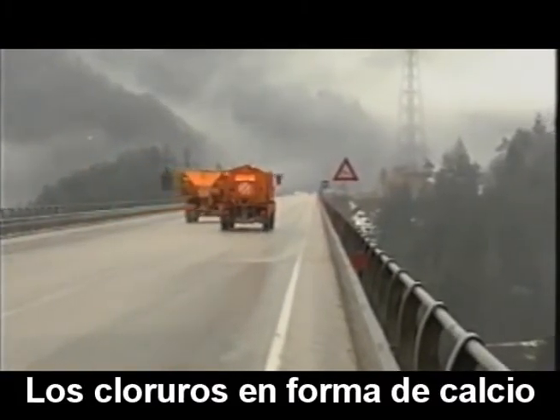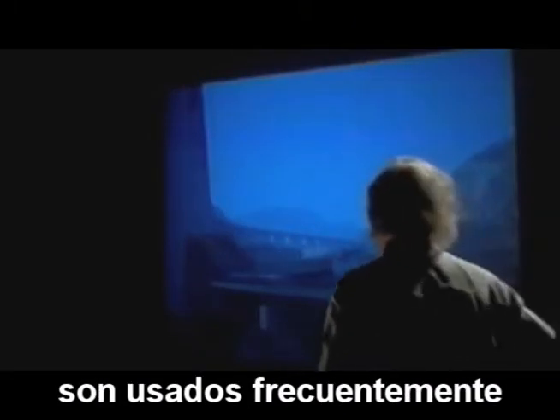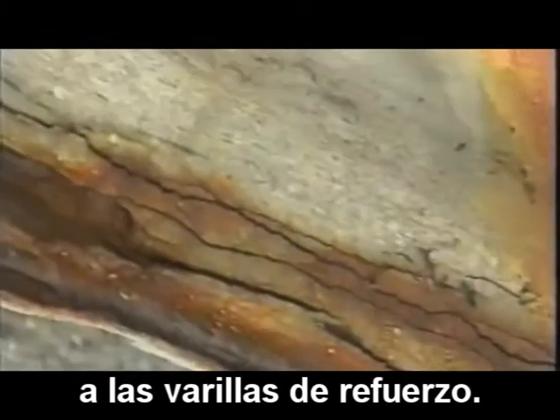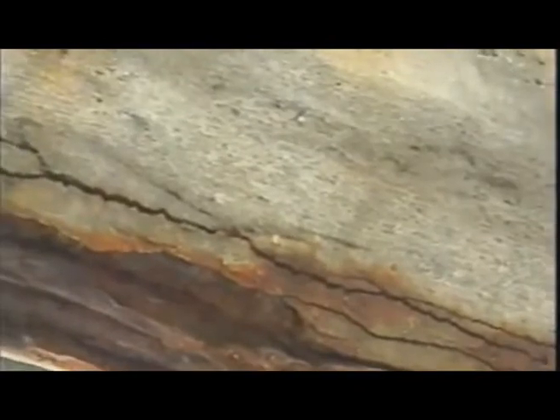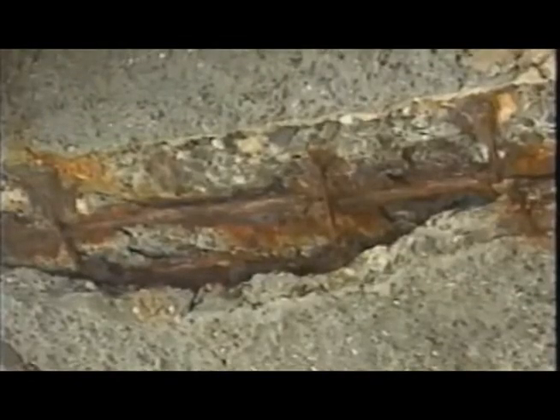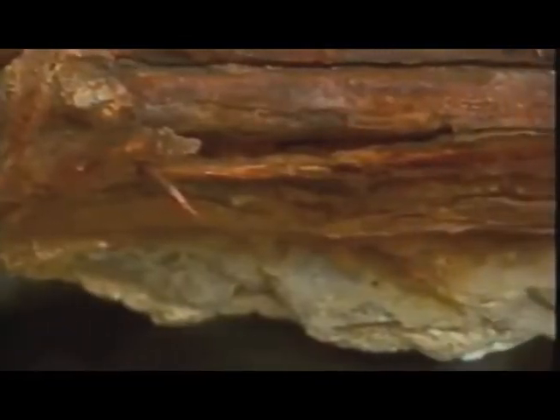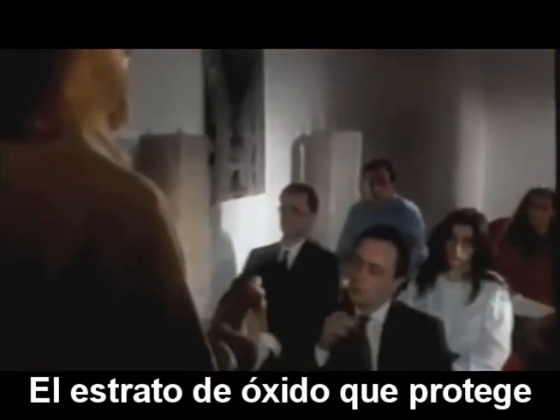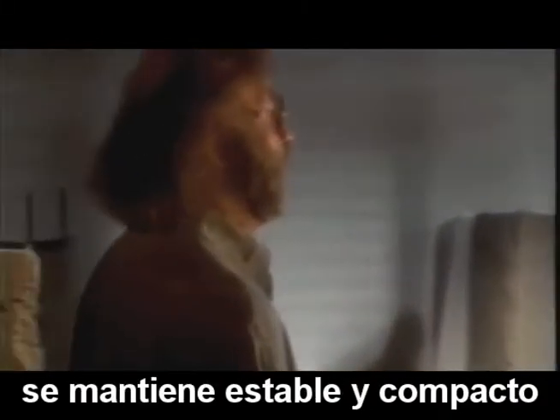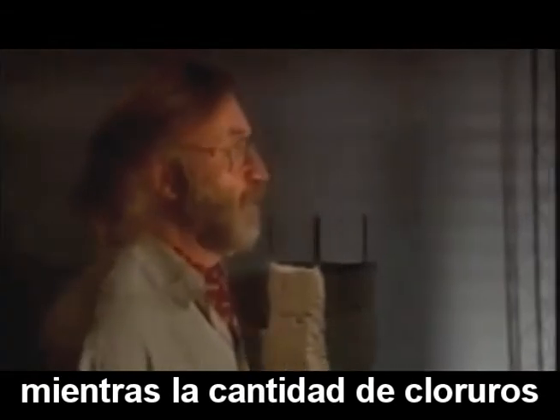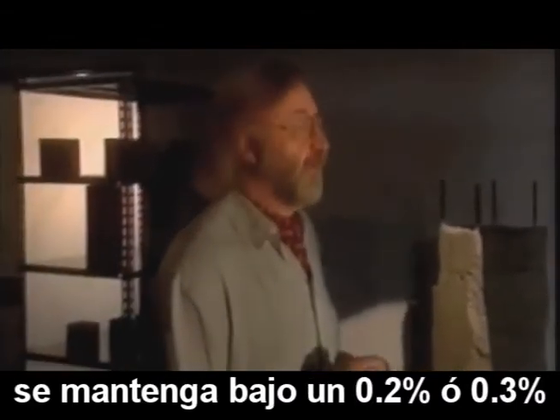Chloride, in the form of calcium or sodium chloride, is used frequently to melt ice. These chlorides can do serious damage to reinforcing bars. The thin rust layer, which encloses and protects the steel bars, remains stable and compact as long as the amount of chloride remains below 0.2–0.3% by weight of cement.